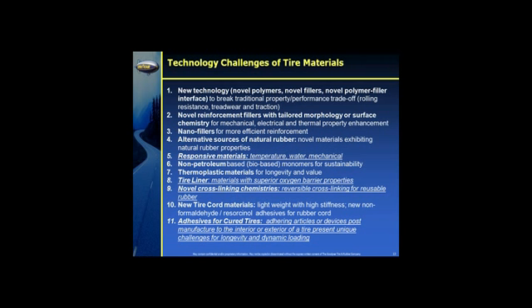Thirdly, think about novel cross-linking chemistries. That is, so that we can do reversible cross-linking for reusable rubber. The diene rubbers used in tires now, polyisoprene, whether it's natural or synthetic, SBR and PBD, polybutadiene, they're cured by the action of sulfur and sulfur-containing small molecules and accelerator chemicals to introduce a fairly low degree of cross-linking, about 1% by molecular unit. This cross-linking does change with age, flexing, and heat. Furthermore, it's effectively irreversible, which poses one of the major barriers to a higher value tire recycling.